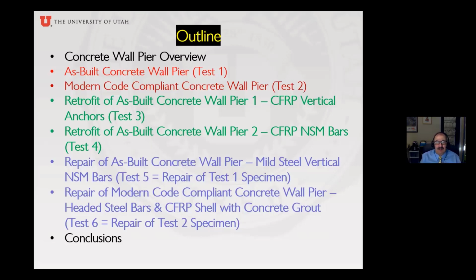But of course, being professors, we like to test as much as we can. So we built these things large scale, about half scale. And so we thought, well, let's take the first test, which is the as-built concrete wall pier, after we tested it and failed it, and let's repair it. So after an earthquake, what would that first pier do if we were to repair it? In the repair, we used mild steel vertical near surface mounted bars and carbon fiber. So that was the repair of the as-built.